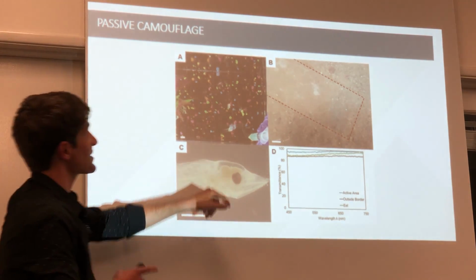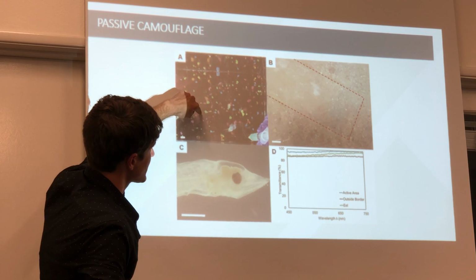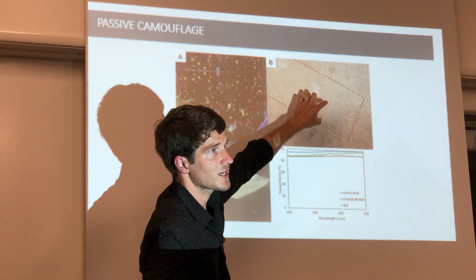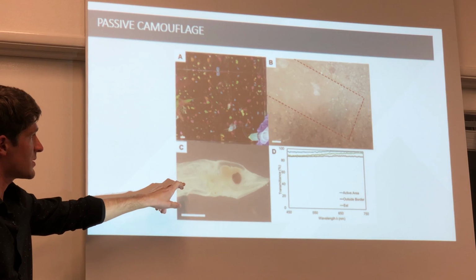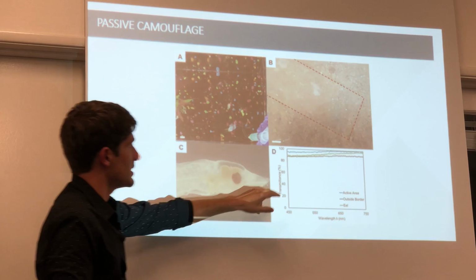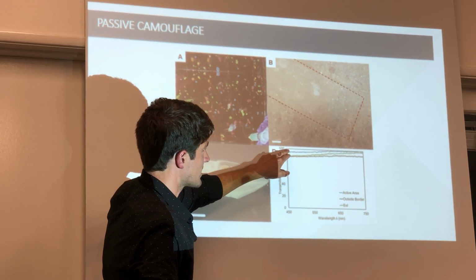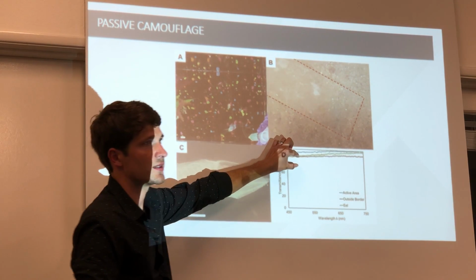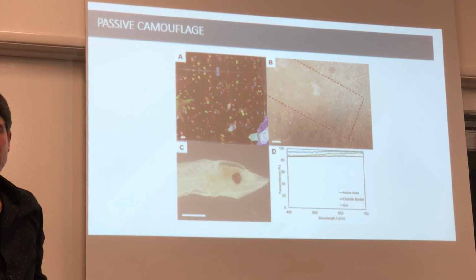What's neat about using water as electrodes is that it's completely transparent, or mostly transparent. It's especially transparent with this light. I can't even see that it's there, but there's an actuator here over some multicolored rocks, and then it's here over some sand. You can see some hazing where the electrodes are, but it's fairly transparent. We compared it to the transparency of an eel, how much light will transmit through the material. The eel is this green line, and the two different parts of the actuator, the hazy part and the border part, are bounded by how transparent the eel is. So it's roughly as transparent as an eel.